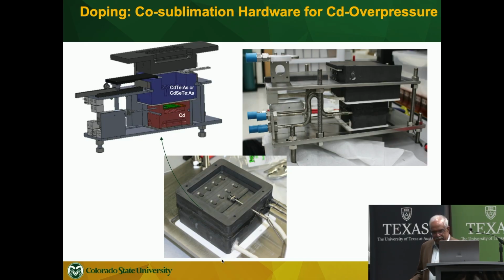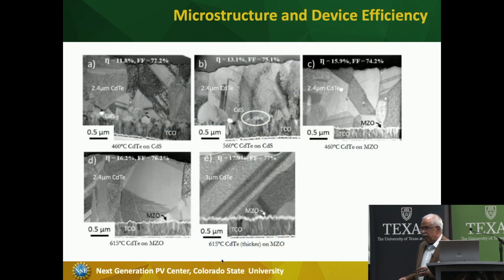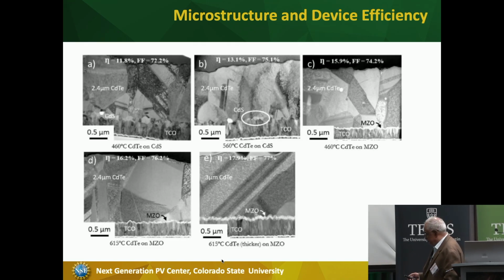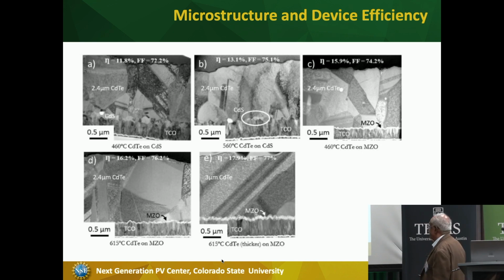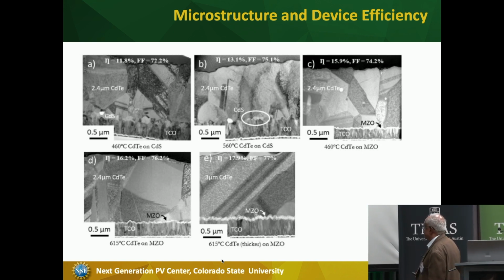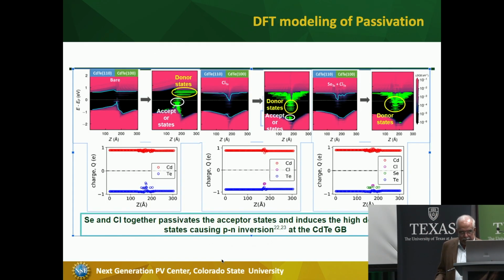Okay, so this is where I was. We do a lot of work, as I mentioned, on understanding what happens in the microstructure. If you had said a few years ago that you could make this quality films and convert this much light to electricity with a microstructure that looks like this, where there are a lot of grain boundaries and a lot of defects essentially, but still make that kind of percentages, it all depends on passivating the grain boundaries. You have to make sure that the grain boundaries are not harmful. And we have shown that progressively modifying the microstructure improves the performance, and that's how we make good solar panels.